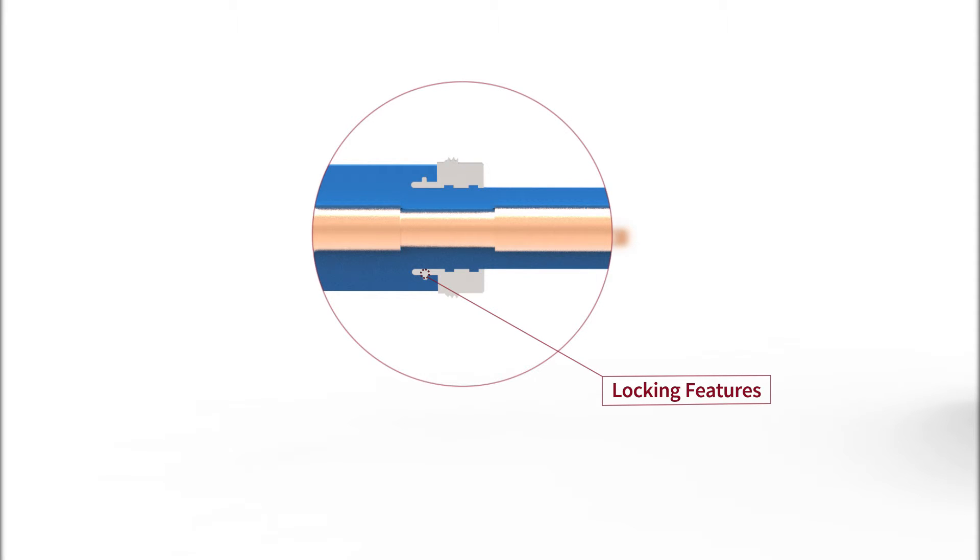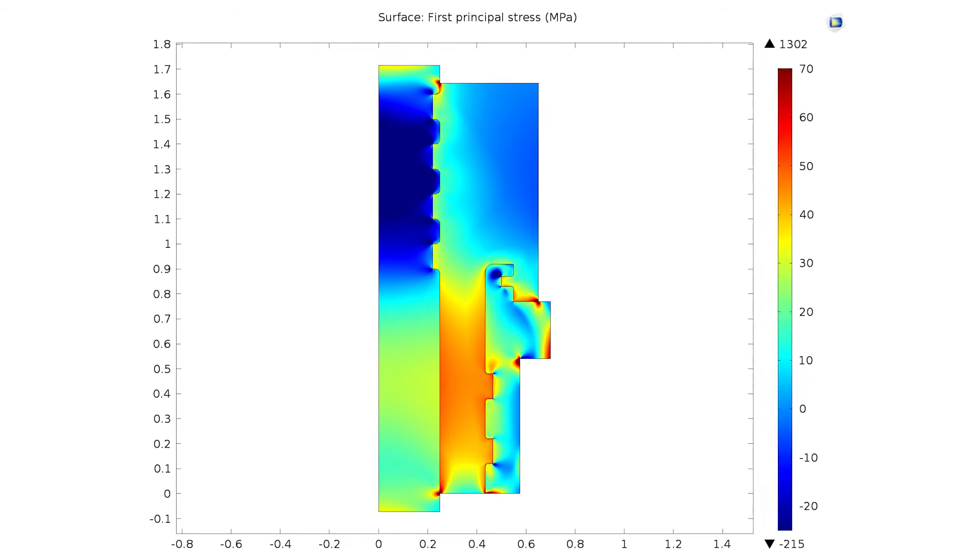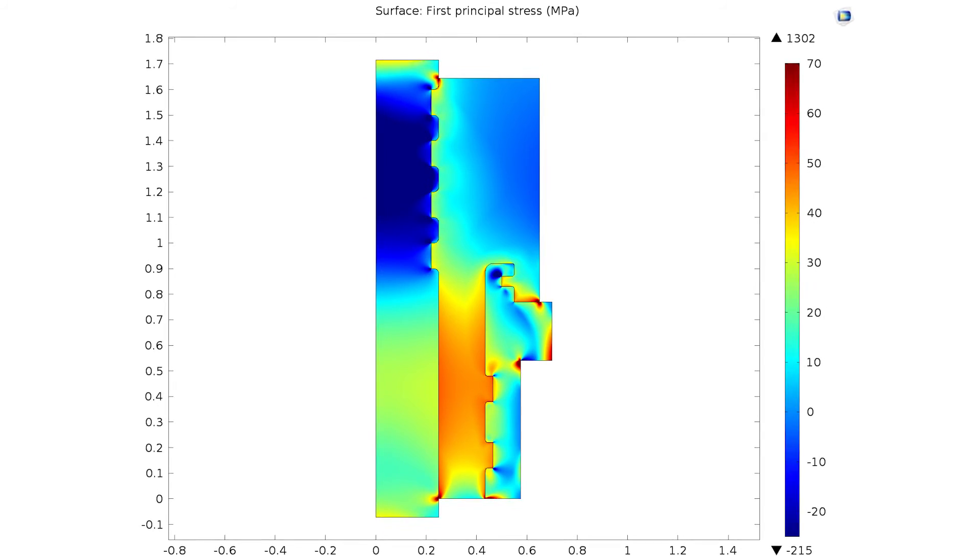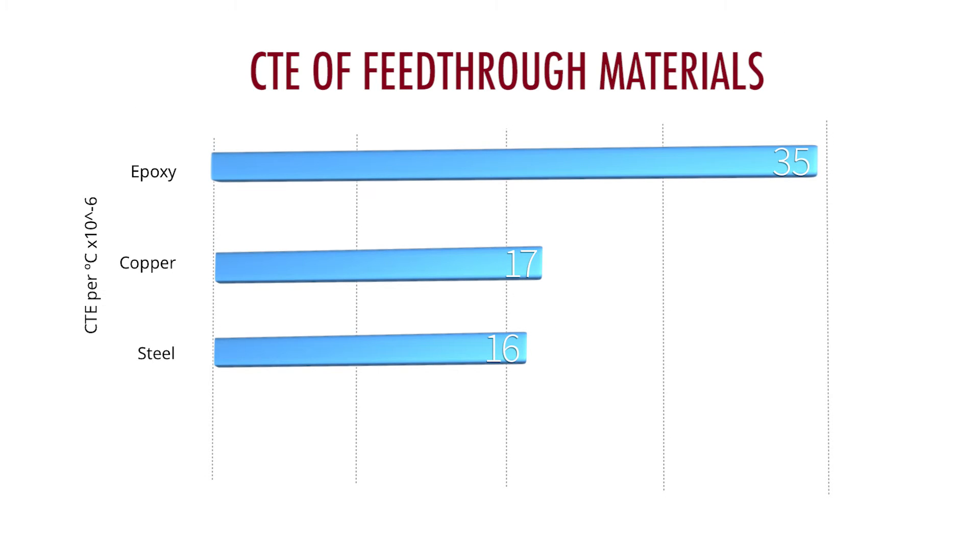This direct seal technology sounds simple enough, but it required many FEA simulations to manage the coefficient of thermal expansion mismatch between the various feed-through materials and the resulting thermal stresses.